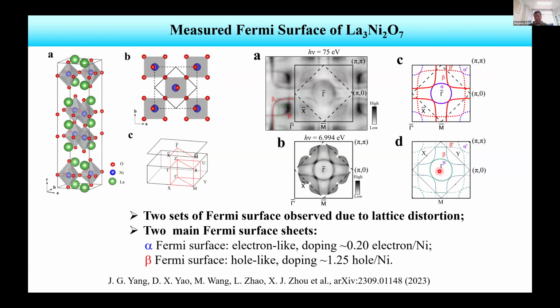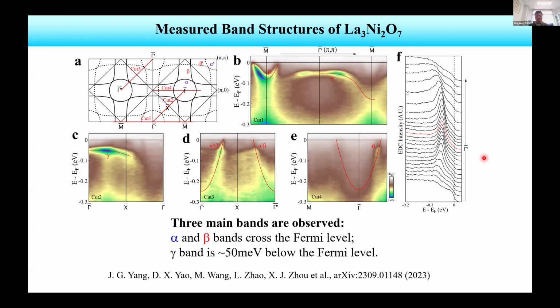This is the Fermi surface obtained from band structure calculation. I think these two are consistent with each other. Then we also measured the band structure along some high symmetry cuts here. Mainly in this case we can really see the alpha band and the beta band along the diagonal direction, which are degenerate.